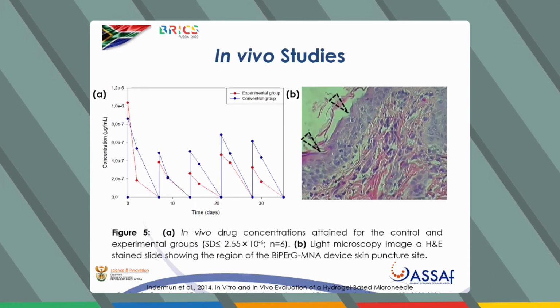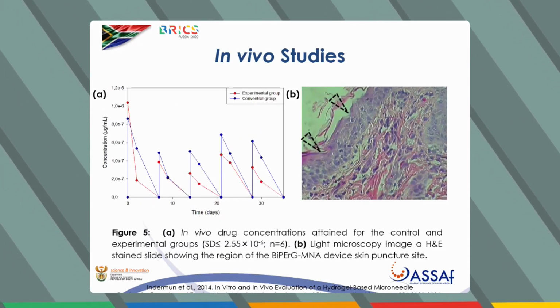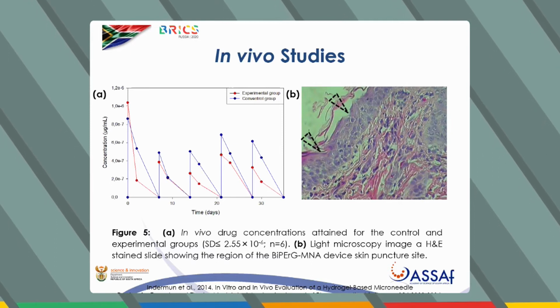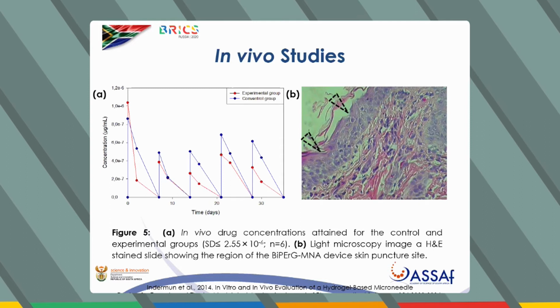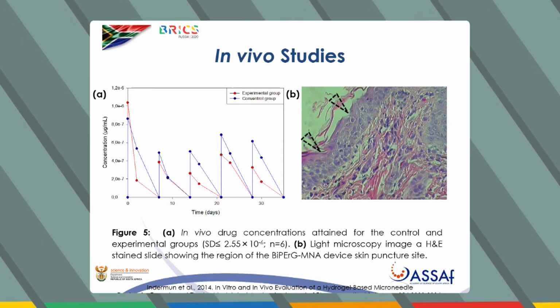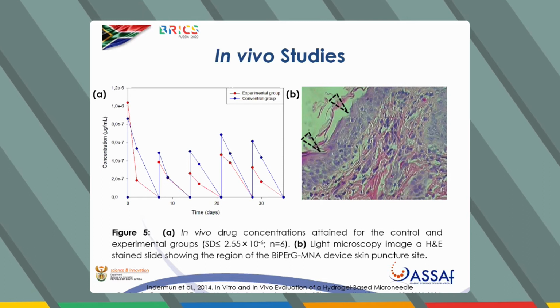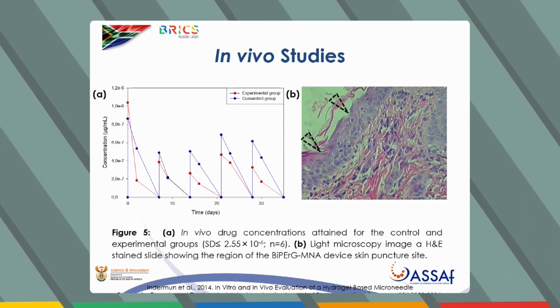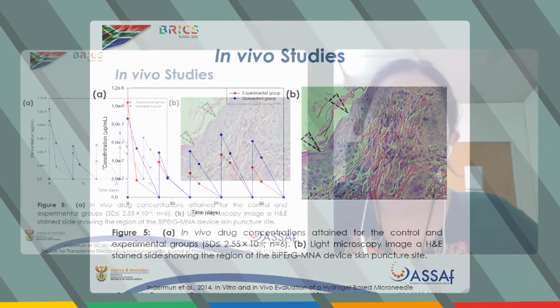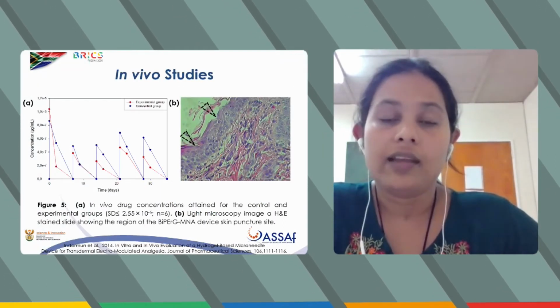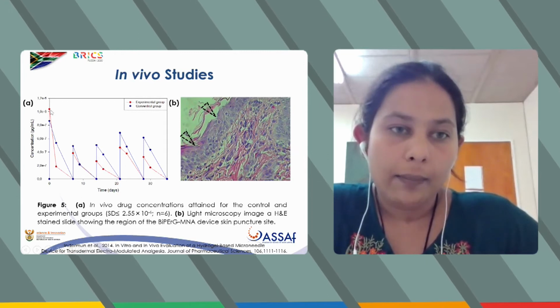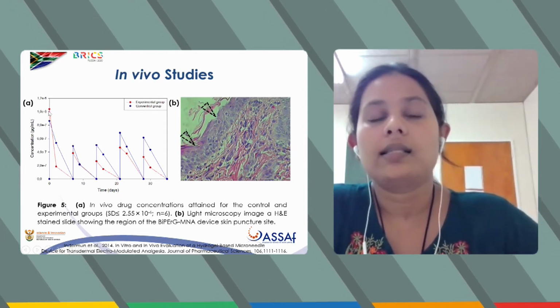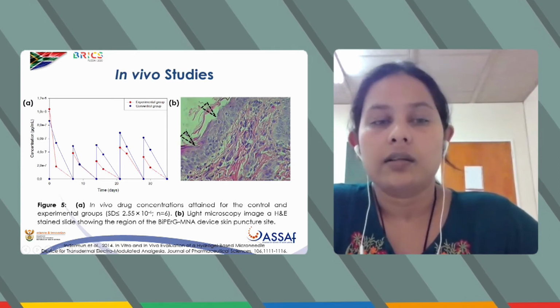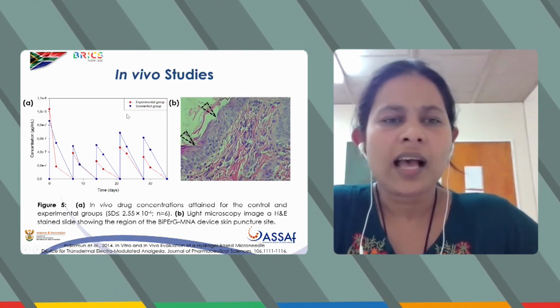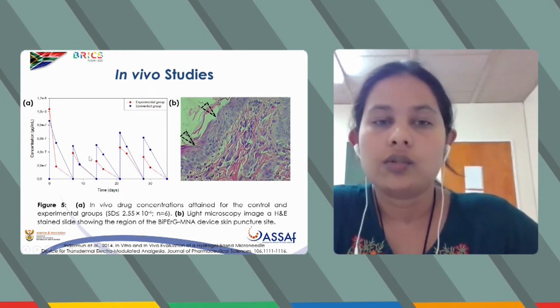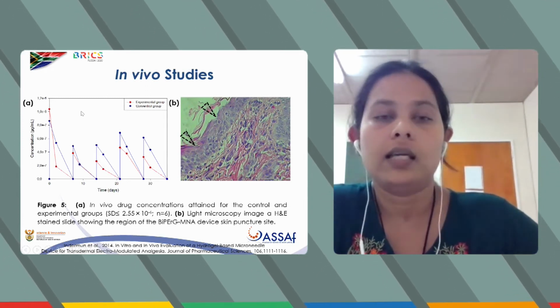So we've also conducted in vivo studies. These were conducted in Sprague-Dawley rats, and it gave a good preclinical indication of the electroresponsive capability of the BiPERG MNA device, with plasma indomethacin levels varying by less than 6.76 times 10 to the minus 7 micrograms per mL, as compared to the conventional IV administration group. We had a peak of 1.04 times 10 to the minus 6 micrograms per mL after the initial electrostimulation. As you can see from the profile, there aren't any fluctuations or any other type of irregularity.